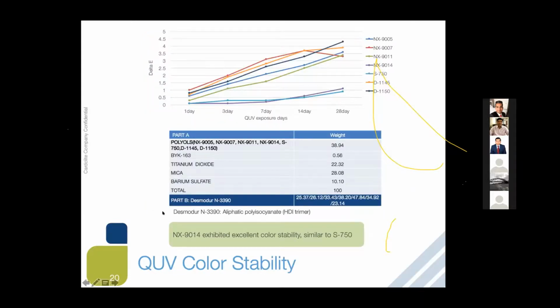Yeah, as I mentioned, one of the products we recently launched, if you look at the purple color, 9014, will give you better yellowing comparative. We did some work against the current market, and we use here an aliphatic isocyanate, not the aromatic polymeric MDI. On the aliphatic side we use Desmodur, one of our Covestro grade N3390. Based on that, we generated the data. So it shows that against the competitor, NX9014 has a better UV property.